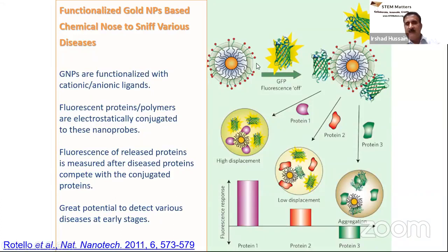For example, in this case, if you incubate these cationic gold nanoparticles with green fluorescent protein, which has overall negative charge, due to electrostatic interaction, these proteins will be assembled at the surface of cationic gold nanoparticles. And the light which is being emitted by these fluorescent proteins will be absorbed by the gold nanoparticle if they are close enough. So in this way, the fluorescence of these proteins is now quenched, and you basically have now a nanoprobe that can be used for the detection of different diseases.